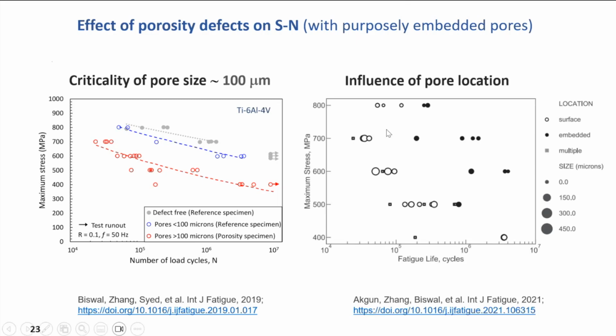The second student carried on with the analysis. He found this very large scatter: if you see the 500 megapascal stress and also the 400 megapascal stress, the life has a scatter factor of more than 2 orders of magnitude. It's not due to the defect size, but actually due to the defect's location. The defects inside the material, after machining into dog bone shape, may be very near to the surface and cause very high stress concentration. So these open circles are surface defects, and these solid dots are the internal defects. That's the contribution to clarify the location being the most critical for fatigue rather than size.